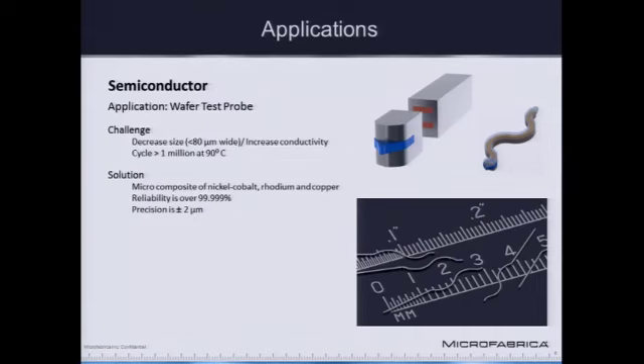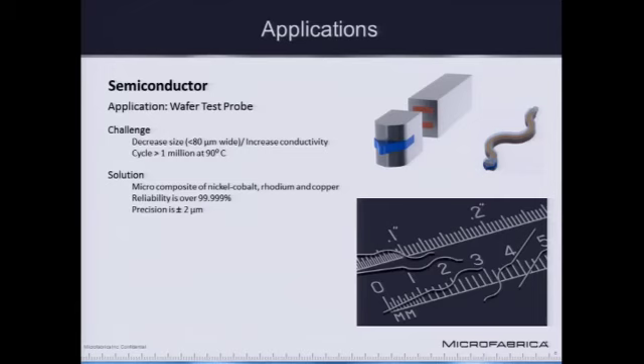So there's this move to smaller dimensions, but then there's also a need for higher power. So they want to have more conductivity, more current to go through these microneedles. In the same way, they still need high reliability. These little micro springs, they look like eyelashes, cycle over 1 million cycles. So our solution, we've been able to make this micro composite device. It looks like a simple little wire.